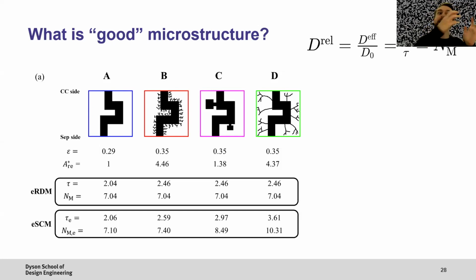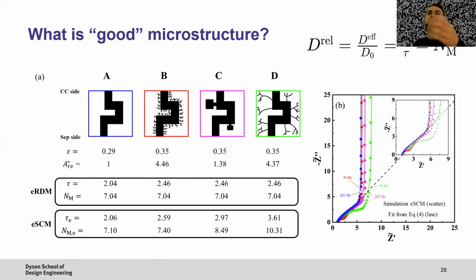So each bit of surface can only host so many things coming in from the outside. So we actually calculate an impedance spectrum, and then we use some analytics to extract from that, with a fit, what that would suggest about the tortuosity of the system. And what you can see is initially, A, B, C, and D are all uniformly bad according to the normal tortuosity factor, but that hasn't told us how easy it was to access the active materials. Whereas the bottom line, or the penultimate line, says, actually, some of these are much harder to access active material than others, and that needs to be taken into account. So you'd always normalize as well by the available surface area. And here's what the impedance box looked like.